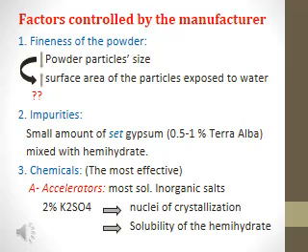If the manufacturer adds more than 2% of potassium sulfate, this amount of potassium sulfate will not act as an accelerator, but it will act as a retarder. It will retard the reaction, increase the setting time. This is because this excess amount of potassium sulfate will deposit or coat the surface of the crystals and prevent its dissolution.